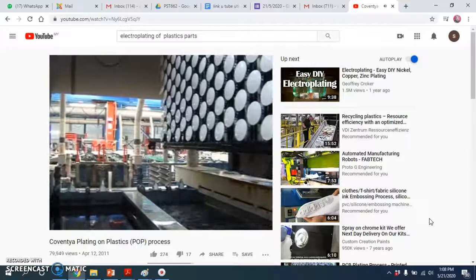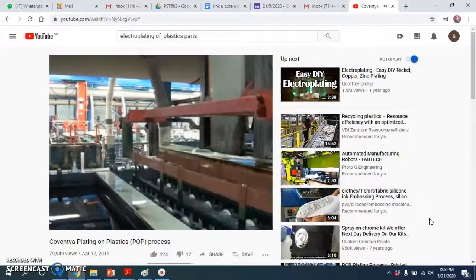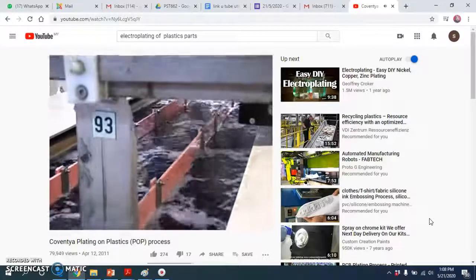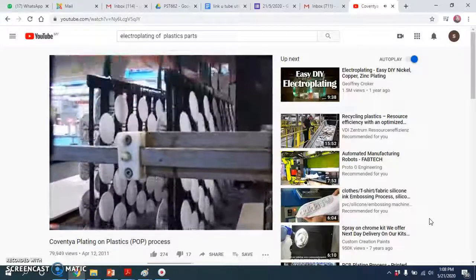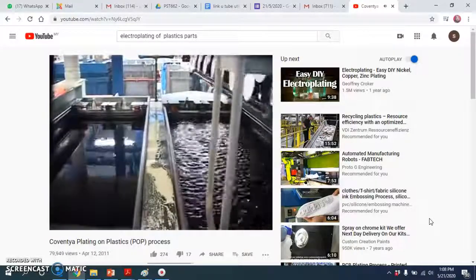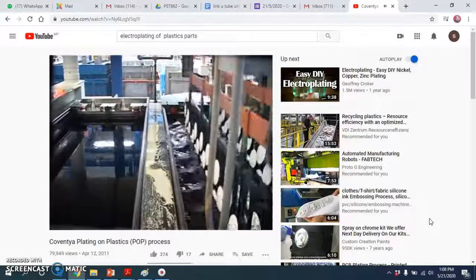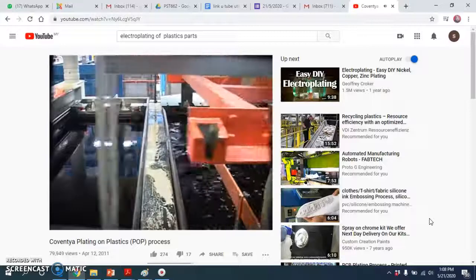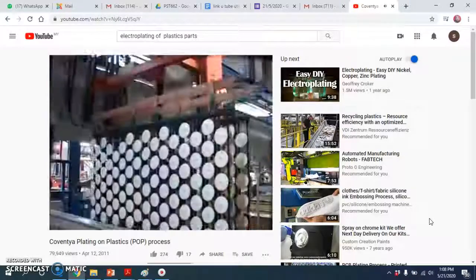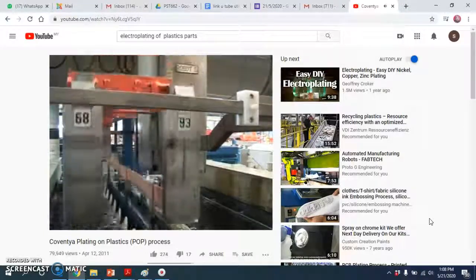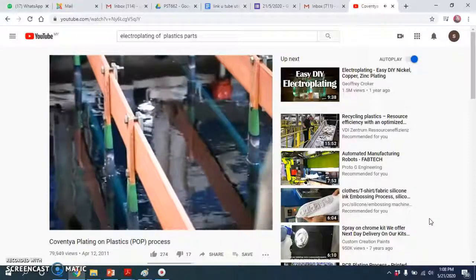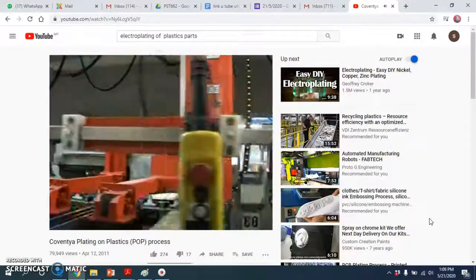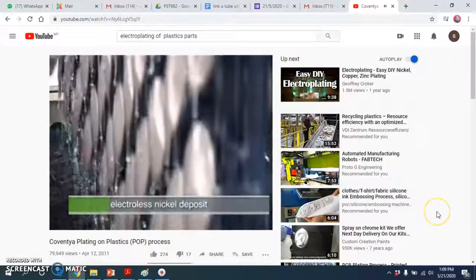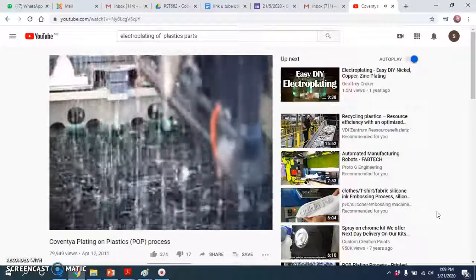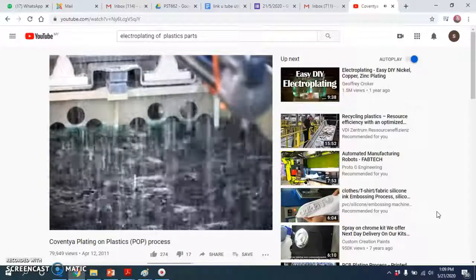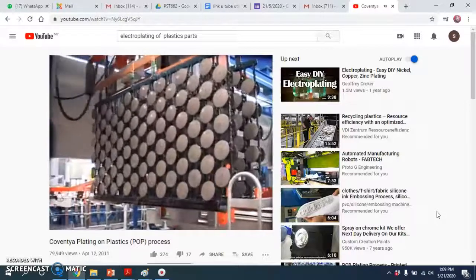Catalyzing the plastic with the controlled absorption of palladium and tin colloidal particles in the micropores is critical for making the surface conductive. The next process is referred to as accelerating the surface, where a chemical reaction takes place to oxidize tin plus 2 ions to tin plus 4, and palladium ions are deposited on the surface as metallic palladium. After acceleration, the surface is ready for a thin layer of a conductive metal to deposit on the palladium catalyzed surface. This occurs from an electroless nickel process step, which deposits a thin, dense nickel phosphorus alloy. The nickel alloy layer thickness deposited from the electroless nickel ranges from 0.2 to 0.4 microns, resulting in the plastic parts becoming conductive, which is very important for the deposition of the copper, nickel, and chromium electroplating sequence.